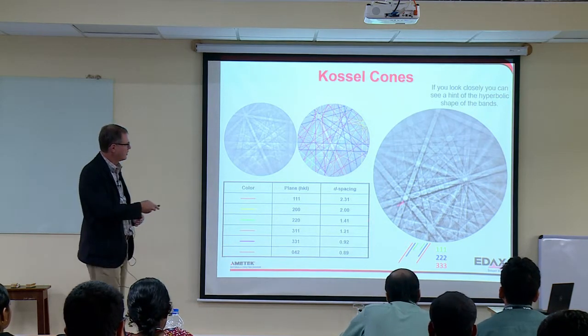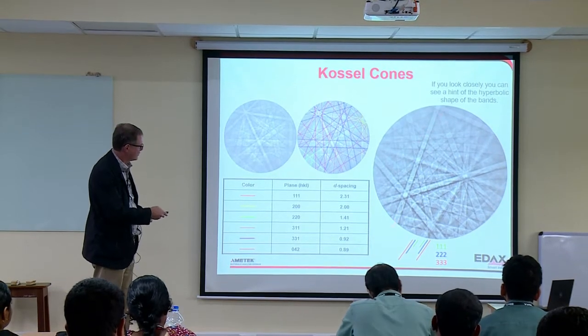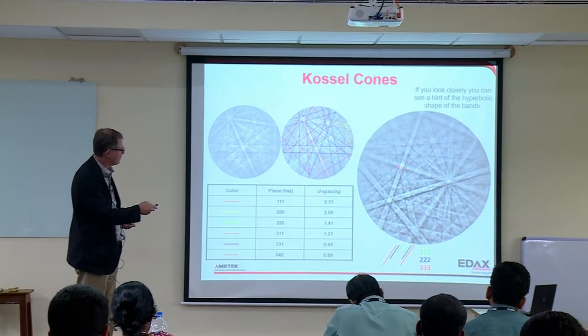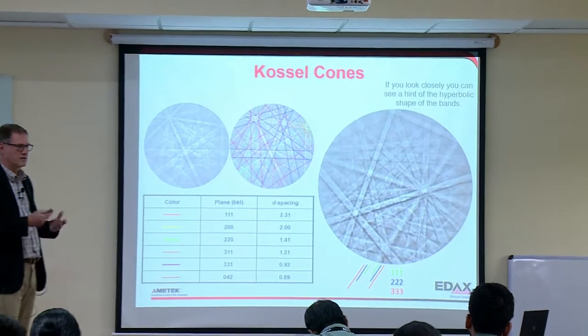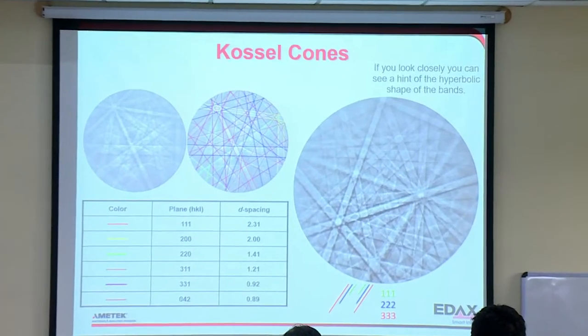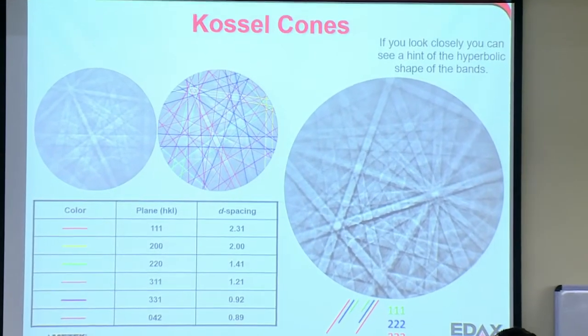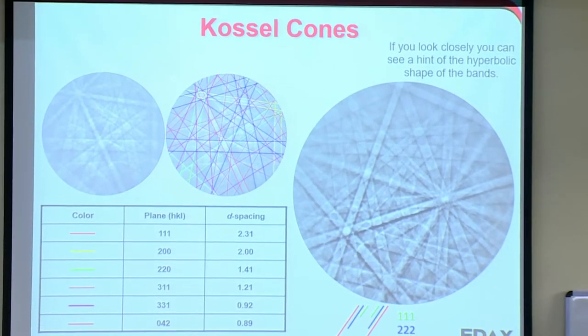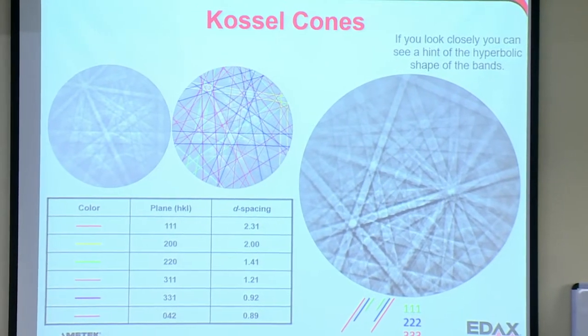And if you look really close, you can see some curvature. This band's a little fatter here and a little narrower near the center. And that's the hyperbolic nature of diffraction. And these kinds of patterns, we call them EBSD patterns, electron backscatter diffraction. But it's Kikuchi diffraction, though we usually think of Kikuchi in the TEM.